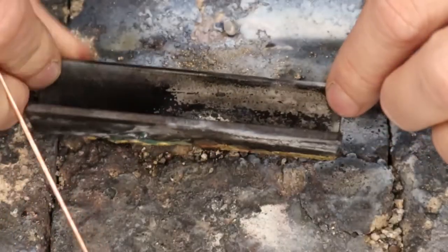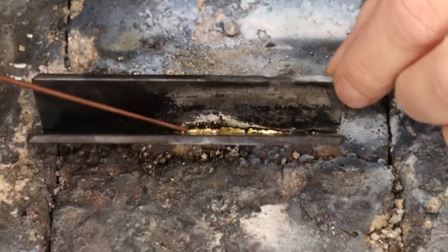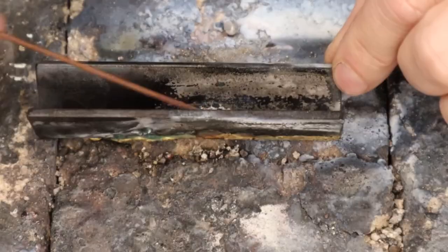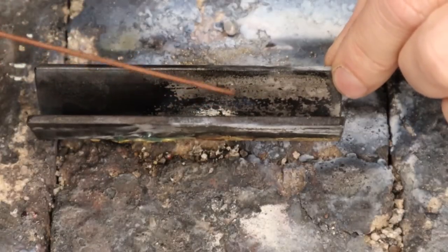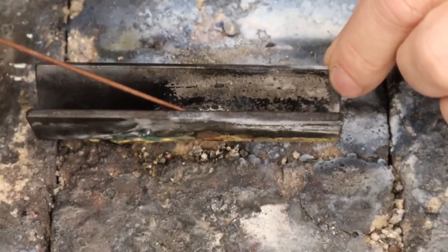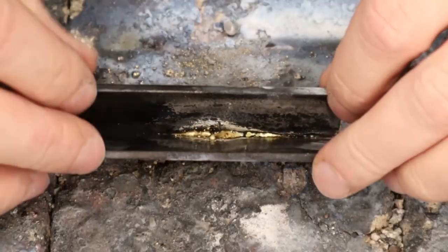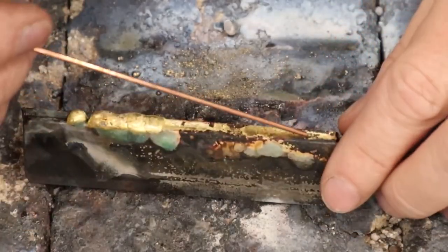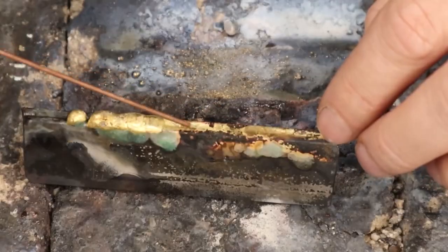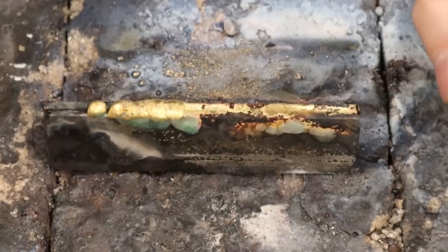And if I flip this over, you can see we actually got some good capillary action where the heat was down in here, and so it sucked that brass right through the crack into the backside, but still not a lot of strength because this isn't filled up, and there's a crease there that we can still see, obviously. So too cold, too hot. Hopefully this will help you guys troubleshoot your brazing samples as you go forward.